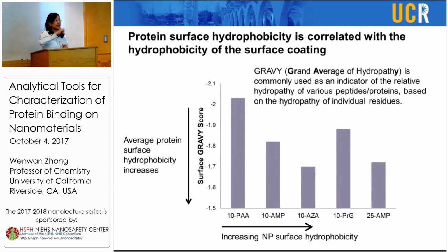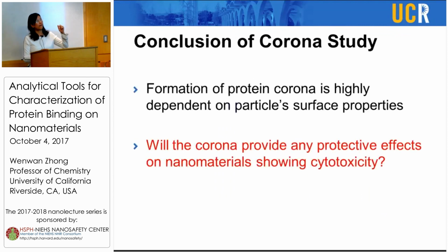And another thing we find out is that when we calculate the surface hydrophobicity of the protein using the GRAVY method, so we use the GRAVY score to represent the surface hydrophobicity of some of the proteins we find in the corona. So we see that if the hydrophobicity increases on the particle surface, then also the hydrophobicity within the protein corona will increase, kind of like dissolve like, right? Or like to bind the surface with similar property. So we see that again, the proportion of hydrophobic protein prefers to bind to the hydrophobic surface, and also the hydrophobicity as well as the size of the particle will affect the dynamics of the corona formation.